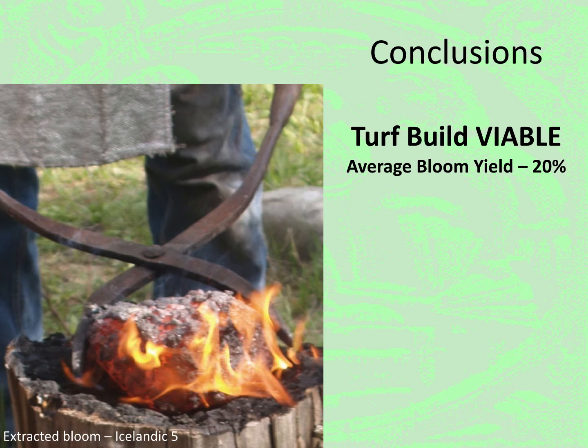Much was learned over this series of 8 experiments. What conclusions can be drawn? First and most importantly, the construction technique seen at Hals of a turf cone furnace inside of a timber box was proved to be viable. Iron was produced in every experiment. Our average bloom production was 20% or more.